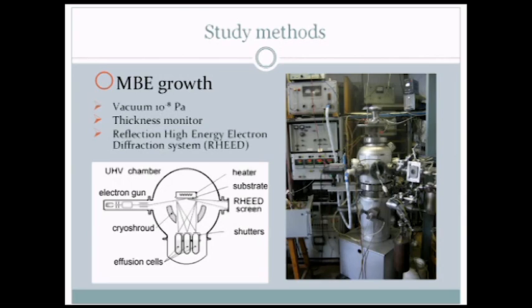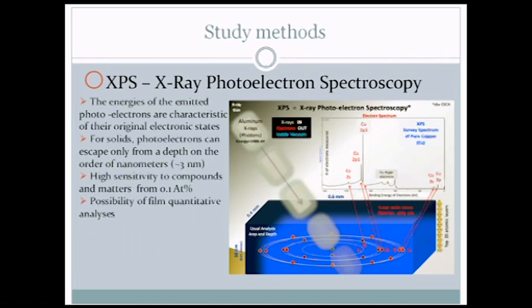Our samples for study were prepared in the vacuum chamber, which you can see on the right side of the slide. Here is a scheme where in the effusion cells there is a material which operates on the top of the substrate, on the surface of the substrate, which can be heated, and crystal structure is controlled with reflected high energy electron diffraction. So you can see if it is a good crystallinity, and you can understand some epitaxial relations through this.